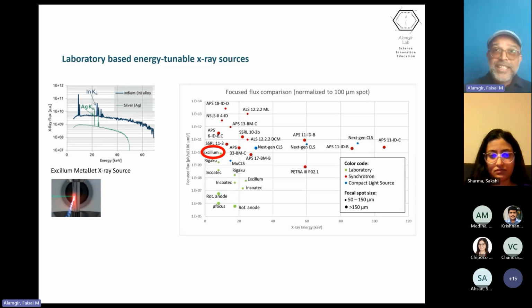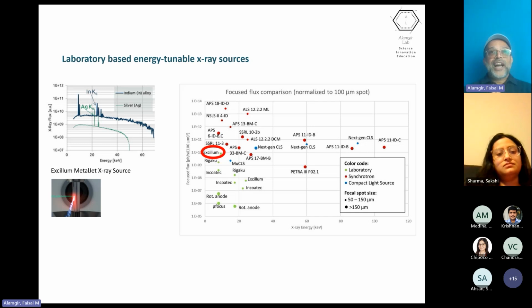So the redesign or the rethinking that you have to allow for is that we are now going to focus on the rest of the X-ray envelope and see whether we can raise the intensity of that envelope higher to be competitive enough with synchrotron sources. It's never going to be competitive in a side-by-side analysis. You're not going to get that many photons, but you can get to the point where it's feasible to do these kind of experiments in the lab, albeit with longer acquisition times.